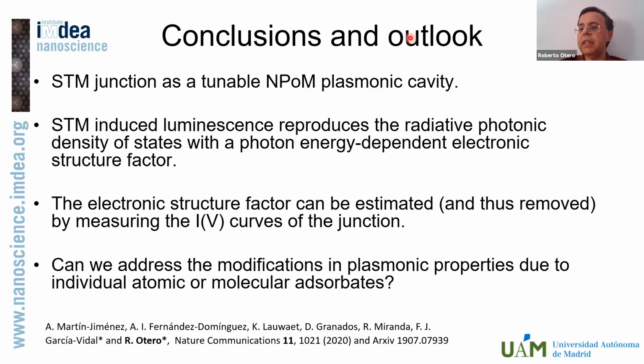The mechanism for this excitonic emission is not very clear. Even more so considering that usually you only use 2 or 3 atomic layers of salt, because of course you want to tunnel through it. So you are very, very close, and it is not very clear why your molecule is not quenched, although after the previous talk, one might have some idea that this should indeed be the case. There's a lot of phenomenology and a lot of work to be done, and a lot of things that are not understood. So our hope is that we are bringing some light as to how to properly interpret these results.